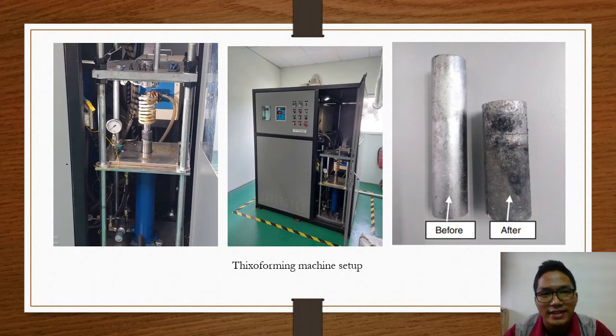This figure represents the thixoforming setup. A bar of cylindrical specimen was cut into suitable slug length and reheated into semi-solid state to be formed in the die. In this process, the specimen was heated by a high-frequency induction coil. A K-type thermocouple was used to control the heating temperature, which is located 5 mm from the top of the slug. The thixoforming process was carried out by using a hydraulic cylinder press after the thermocouple was removed from the specimen.